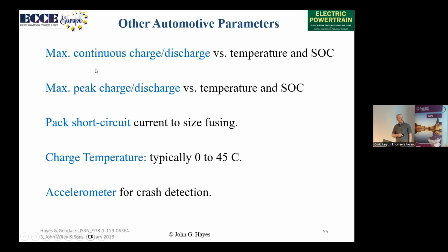Other parameters, we have significant max charge and discharge in an automotive, significant max, that's continuous. Then we have peak. We have to protect against short circuits. That comes down to fusing and other factors. We've got to be careful about charge voltages or charge temperatures. Typically, we don't like to charge sub-zero because that can cause dendrites to form and the lithium to build up on the anode. And we may need an accelerometer separately in the pack, just in case we have a crash condition, and we can ask the contactors to open if there is a crash.